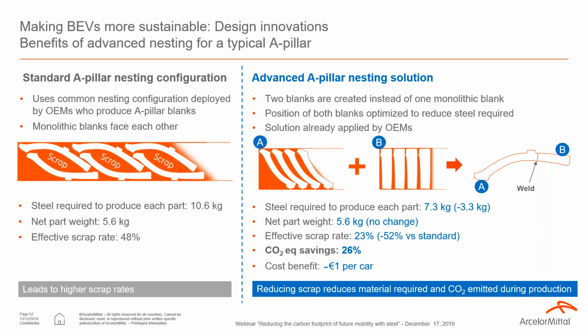Basically, with the standard process, we have a scrap rate of 48%. But if we decide to cut the blank in two and to weld it afterwards, even if we take into account the welding step, we achieve here a CO2 equivalent saving of 26% compared to the monolithic solution. And of course, it is transparent for the OEM because it's the same material, same thickness, and technically the parts, even with the weld, will behave in the same way. We can also highlight a very interesting cost benefit because in this case, we can save more or less €1 per car.